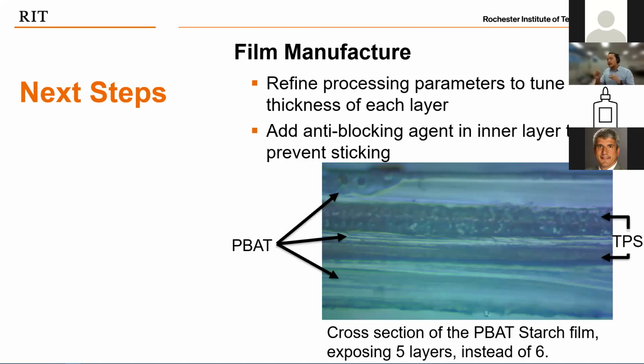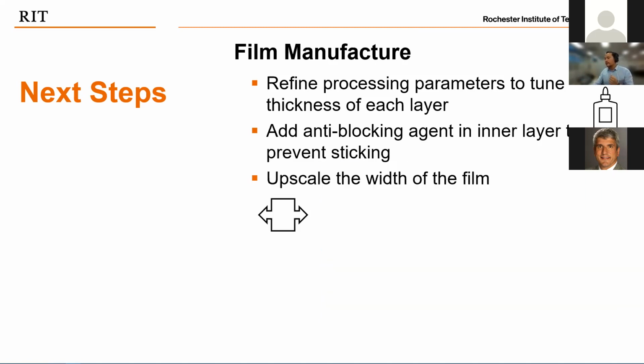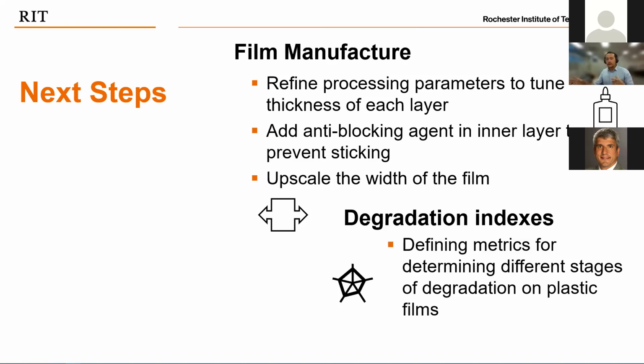If you look at the picture, we have a middle layer of PBAT in the middle. So the thickness should actually be half of what we got. And we have to then maybe add an anti-blocking agent into the inner layer of PBAT, so that doesn't happen. And also we have to upscale the width of the film. As the professor was saying, width is an important parameter that we are a little bit low on, and we have to get it bigger.